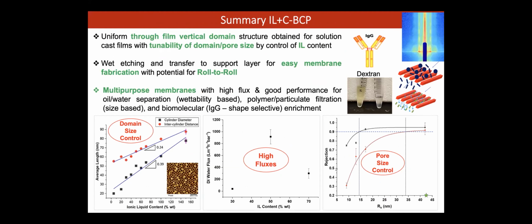So I'll end here. I think that the ability to modulate block polymer membranes with ionic liquid is a big open field now. And the fact that we can use the ionic liquid for ionic separation or remove it and then do size and chemistry-based separation, chemistry hopefully for the future. But what's the advantage? You get high domain size. You get domain control. You don't have to create a new block polymer of different molecular weight for every filtration requirement. You get very high flux, as I showed you on the chart that ours was substantially higher. There is a trade-off between rejection and flux, and that is controllable.